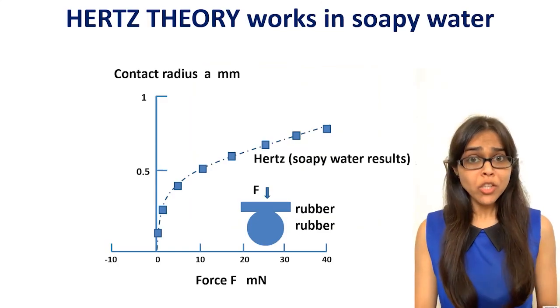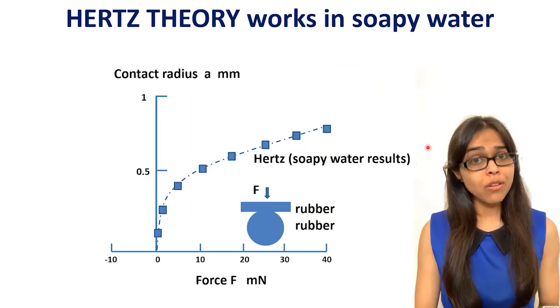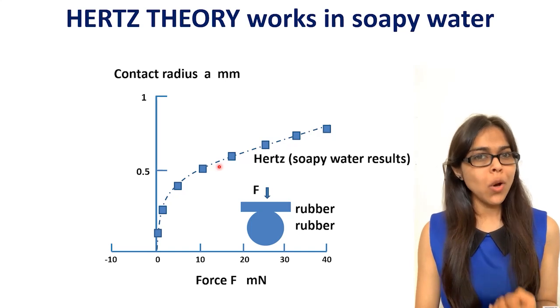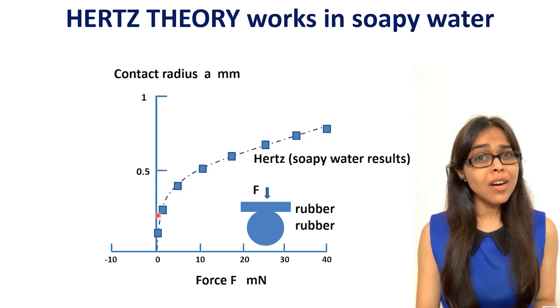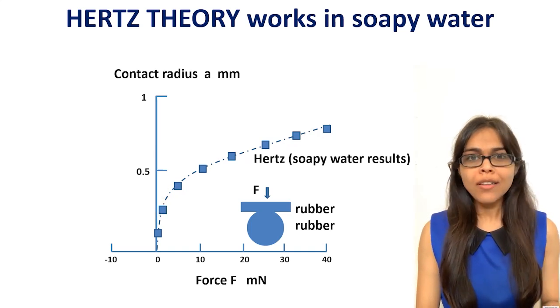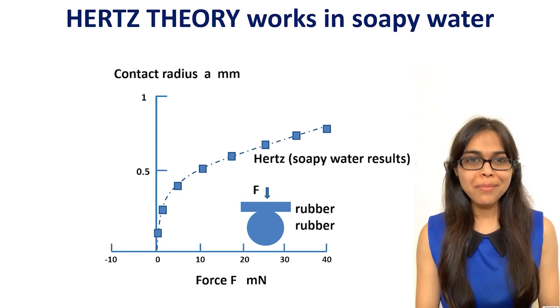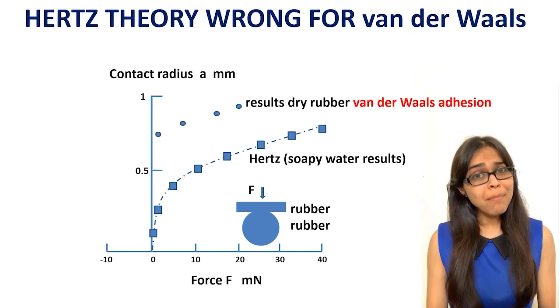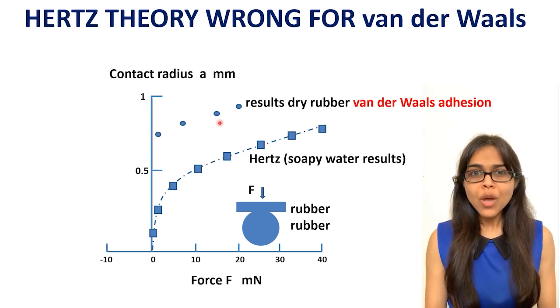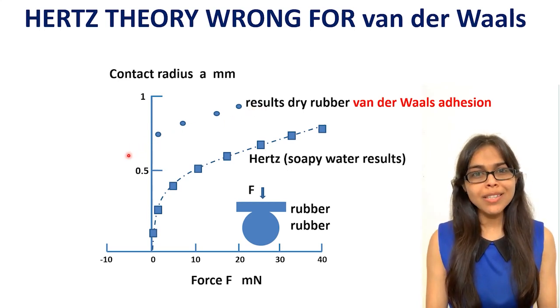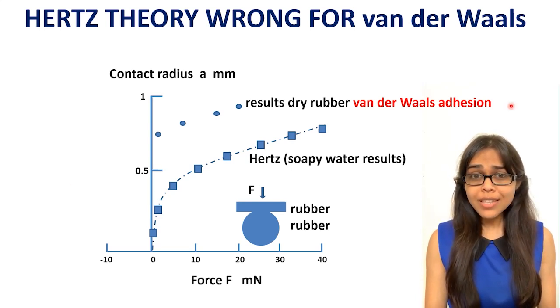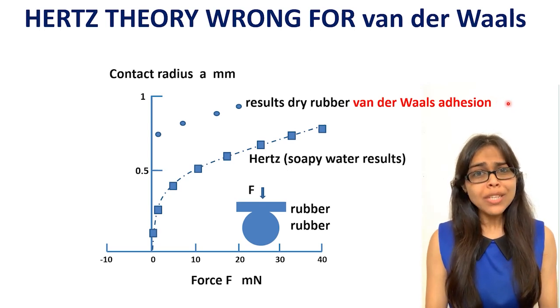From this plot of theory versus the experimental results, the soapy water contact radii fitted the Hertz cubic theory very well. There was no adhesion there. But the dry black spots, they were much bigger, and a tensile force was needed to pull them apart. The conclusion was that the discrepancy in the dry results was a definite measure of van der Waals force. But how can you produce a theory to explain that?